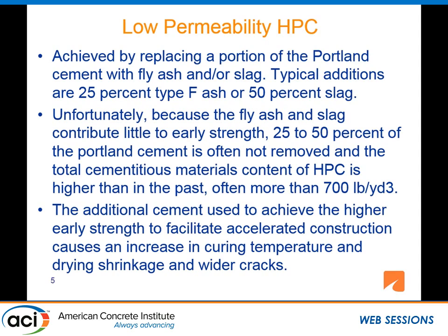Low permeability. We've been able to get very low permeabilities in our high-performance concretes since the beginning of these concretes in the 90s. And it's typically achieved by replacing a portion of the Portland cement with fly ash and/or slag, sometimes silica fume, but most often fly ash or slag. And in Virginia, typical additions are 25% Type F ash and 50% slag.